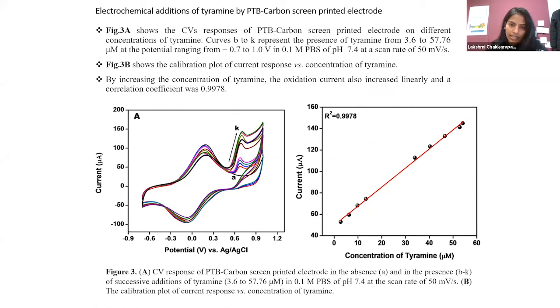Here you could see in figure, the small a is the modified electrode. It doesn't show any oxidation peak at 0.65 volt because we didn't add tyramine the first time, and then B to K represent the different concentrations of tyramine. It's added slowly, step by step. So each addition shows a high current response at 0.65 volt. The linear calibration plot shows the concentration of tyramine versus the current response. When the concentration is increased, the current also increases, because the current and concentration of tyramine are directly proportional to each other.